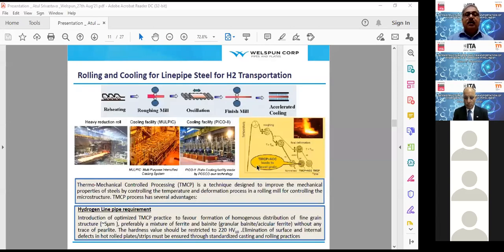The TMCP rolling is going to be very important. I'll not go into the details of this, but this is from one of our very esteemed steel suppliers. What is critically required for steel to qualify for 100% hydrogen transportation is going to be the fine grain structure, preferably 5 micron, a microstructure of more ferrite and bainite, preferably granular bainite or acicular ferrite, without any trace of pearlite. Pearlite will be very harmful for transportation. The hardness has to be restricted to 220 HV10 for the base, and 235 HV10 for the line pipe, including the weld and HAZ.